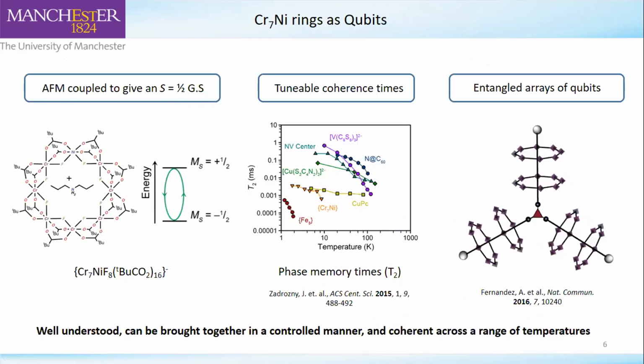So just to delve into the chromium-7 nickel rings a little bit more, because that might be one that not many people have really encountered before. These are 8 atoms, 7 chromium ions and 1 nickel ion, that are antiferromagnetically coupled to give a spin-half ground state. They have tunable coherence times, so we can change the ligands. Normally this pivalic acid is bringing the rings together, and we can change those out and tune our coherence times based on that, for example.